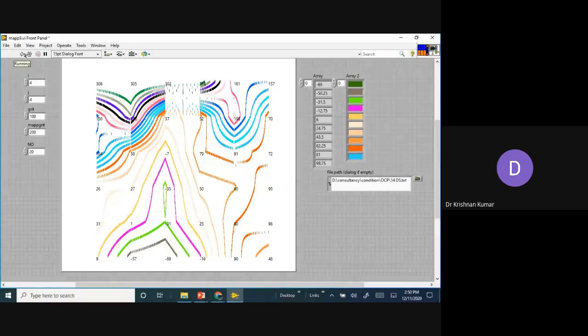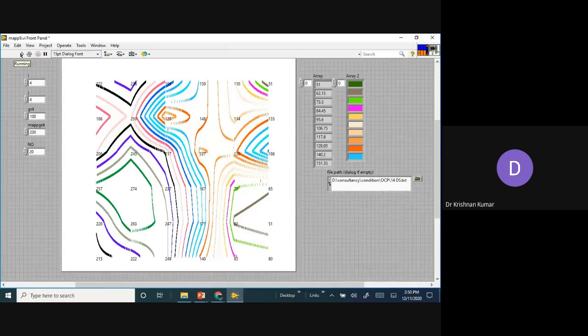Automatically we get the mapping. In that mapping, wherever there are lower potentials, the grayish color, that area is highly vulnerable. We identified this location in the photograph, exactly on the location also, and marked it: you have to do repair at those locations.